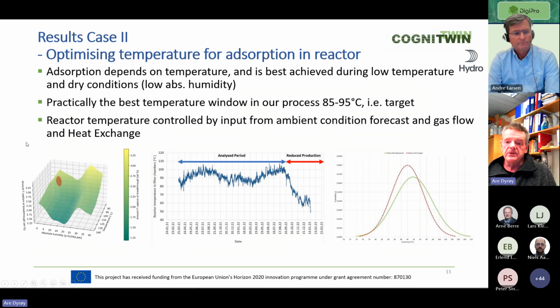In order to keep the temperature, we have an internal heat exchanger in the GTC, and we managed to keep, when it was normal production, within the sweet spot as marked on this figure here, both in terms of humidity and temperature during the period which we analyzed. Then we were prone to some curtailment in our process, which gives us a lot of deviation from the system. But as can be seen here when looking at the data, most of our temperatures were within the desired span of operation.